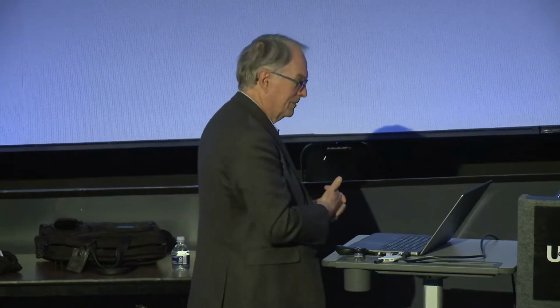Thank you for coming, Stan. You showed a graph of the stability from that Korean group. I think the nickel compounds were the most stable. Do you know what causes that? What is the reason behind that trend? No, the nickel compounds are the least stable. Least stable, sorry, yes. Because nickel 4+ is less stable than, say, manganese 4+ or cobalt 4+. So it wants to evolve oxygen, and if you had the right catalyst, it would evolve oxygen at room temperature, I'm sure. No one's actually measured the effective partial pressure of oxygen in these materials, but my betting is it's above an atmosphere at room temperature. So it's a fire waiting to happen, if that's the way of putting it.